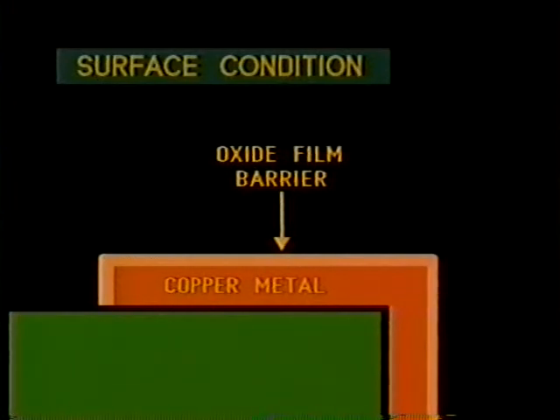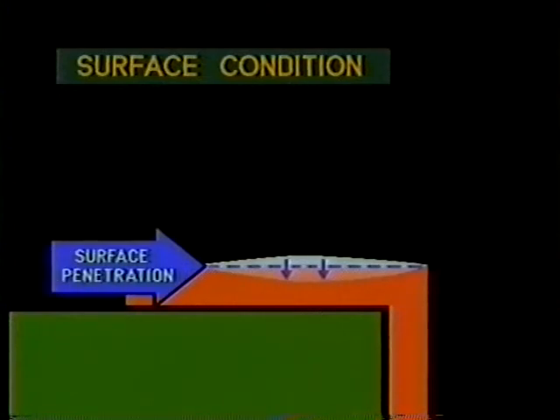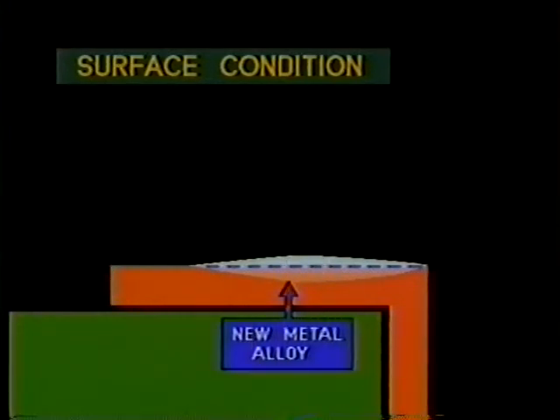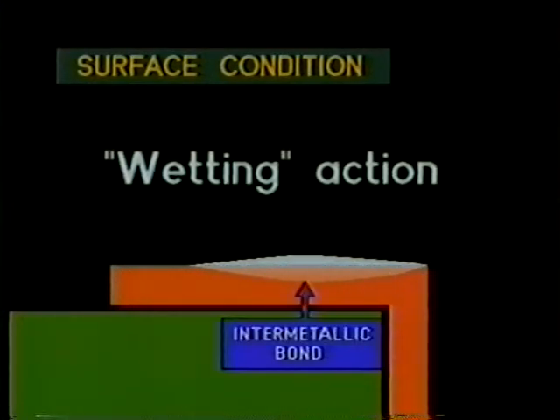To remove oxides and keep them removed during the soldering operation, a natural or synthetic rosin called flux is carried to the work surface as a core in the strand of solder. Flux melts at a lower temperature than solder, and so starts the corrosive fluxing action of removing the oxides and preventing the reformation of new oxides before the solder is fully liquid. As the hot solder comes into contact with the copper surface, a metal solvent action takes place. The copper dissolves and the solder penetrates the surface. The molecules of solder and copper blend together to form a new metal alloy. A metal that's part solder and part copper, with characteristics all its own. The solvent action is called wetting and forms an intermetallic bond between the parts.